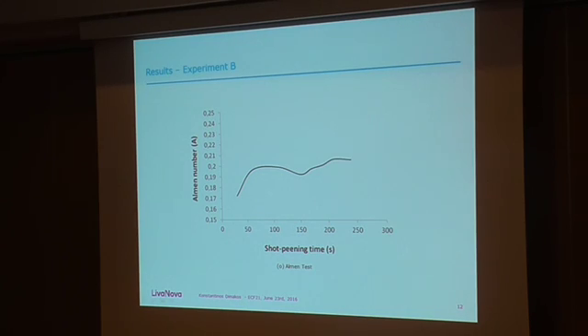Going back, looking at the results of experiment B, we did have some complications here. What happened here is one of the samples, although it was shot peened more than the samples here, it broke. Things happen, but basically, this operation was manual. So I was holding the gun. And the sample is quite small. And because in the shot peening machine, there's also a filter that tends to blow once in a while and scares me as well. So it tends to kick the gun backwards. And holding the peening gun for 10, 20 minutes, it's not easy. But this is a start. You can see, at least, that there's a saturation curve here.